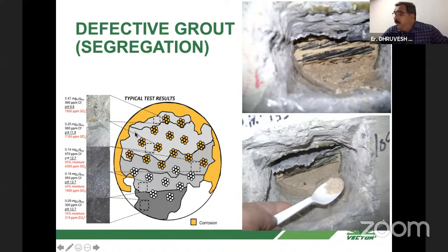And when you check it, remember that normally in RCC, if the chloride content is less than 0.6 kg per m3, then it is safe, and sulfate content is less than 4%. But if your grout has less chloride content but high sulfates, then also it will aggravate the corrosion if there is moisture, because of the presence of sulfate. There is one report, it's a huge report, I can share if somebody wants that. This was surprising to me also, but sulfate along with chloride really increased the rate of corrosion in the case of PT strands. You can see the quality of the grout in the right hand pictures.